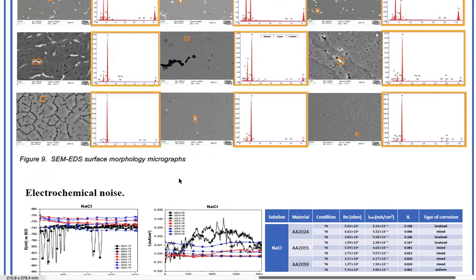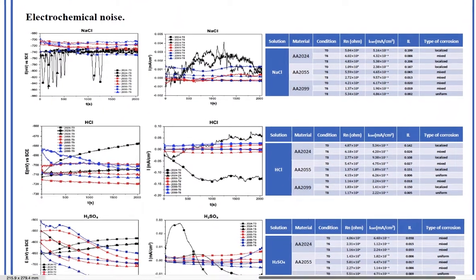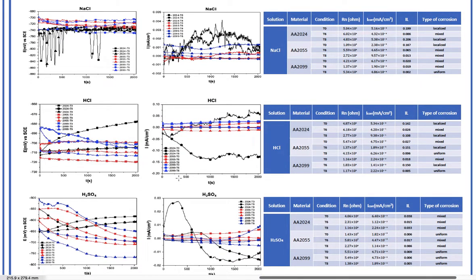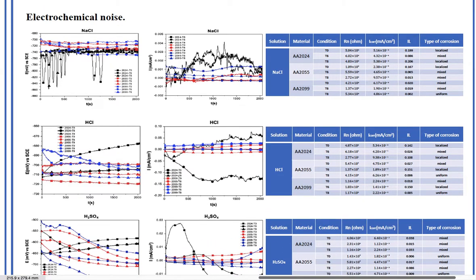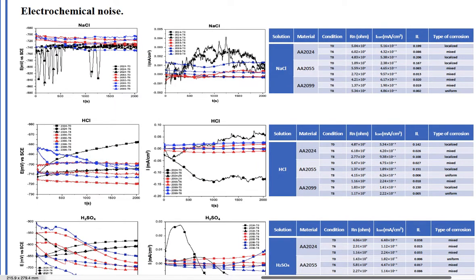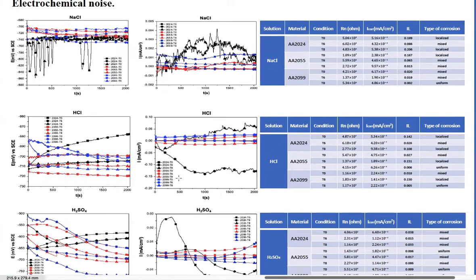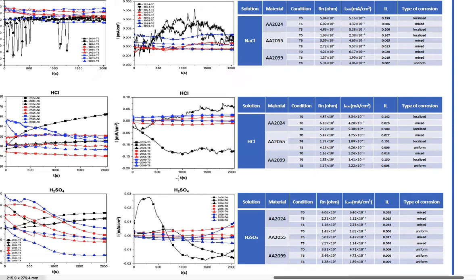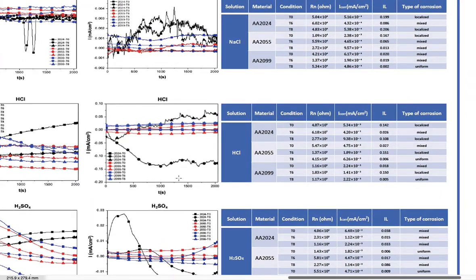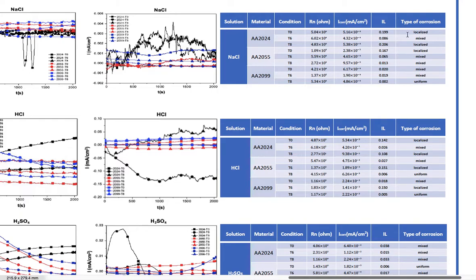The visual analysis of the electrochemical noise results shows unstable signals with high amplitude transients in the 2024 T0 and 2024 T8 alloys, which can be attributed to the amount of precipitates on their surface and may be generating galvanic couples. This is confirmed by what the localization index values indicate in the statistical parameters analysis tables. Localized corrosion.